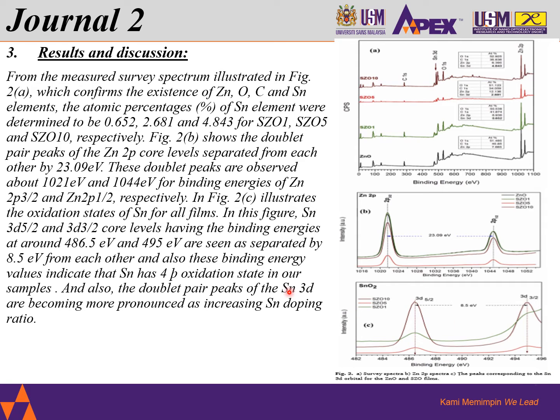respectively. Figure 2c illustrates the oxidation state of tin for all films. In this figure, the tin 3d 5/2 and 3d 3/2 core levels have binding energies at around 486.5 electron volt and 495 electron volt, separated by 8.5 electron volt from each other. These binding energy values indicate that tin has a 4+ oxidation state in our samples, and the doublet peaks of the tin 3d become more pronounced as the Sn doping ratio increases.